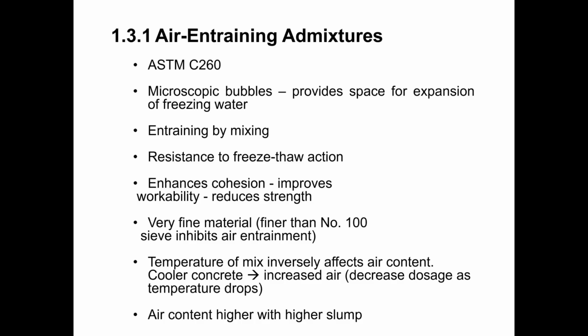It's very similar to if you put liquid soap on your hands and then started rubbing your hands and you get this generation of foam. That's analogous to what's happening in your concrete when you put a liquid air entraining admixture in. Once that liquid air entraining admixture is exposed to the mechanical energy of the mixing process, then it starts producing these microscopic bubbles which get distributed throughout the matrix of the concrete mix. All right, so the key component of the air entrainment is the mixing process, putting the admixture in during the mixing process. If we put some air entraining admixture into a concrete that had already been mixed, then it really wouldn't do anything as far as causing air entrainment to occur within that mix.